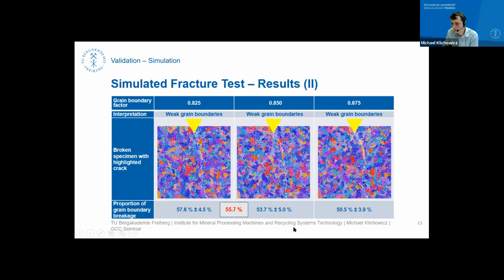And of course, we can now do some parameterization and find a suitable grain boundary factor which imitates this real breakage process, which is somewhere in between 0.825 and 0.85. So we have weaker grain boundaries in the simulation, and we use this realistic mineral microstructure.